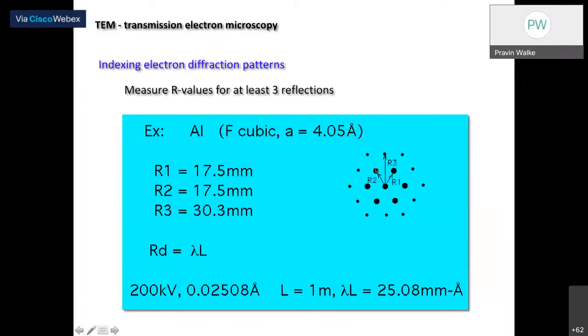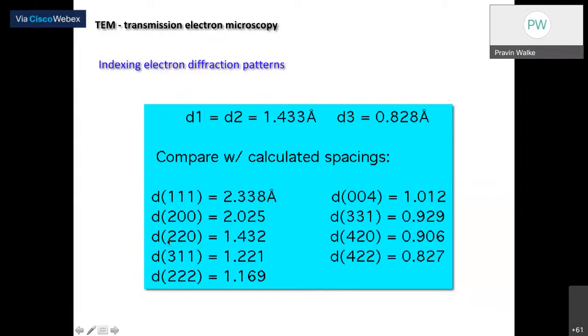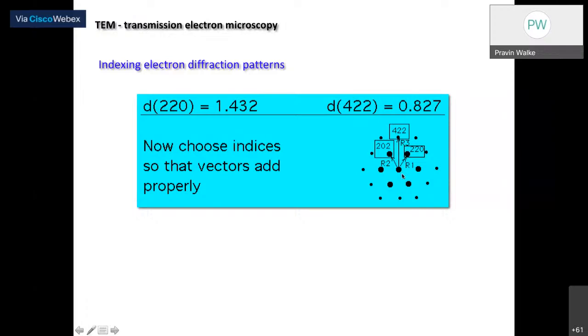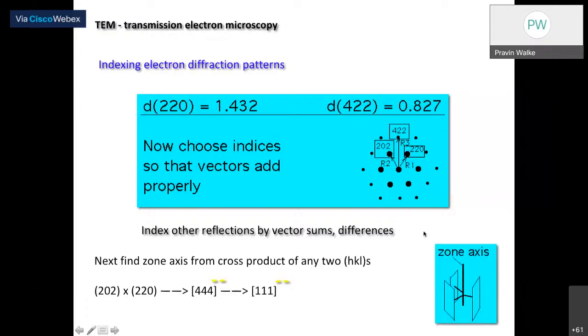Once you know this, let's say you have the diffraction pattern, you can simply find the distance between these consecutive neighboring spots, and you can find the R1, R2, and R3 values. Then by using the formula which we have already seen before, you can find the D values, right? D is the interplanar spacing, D1, D2, and D3 in the specific plane. Then you can compare these values with, for example, the D220 and D422 values, which are 1.4 and 0.8. If the distances between these spots match those D values, then you can simply index those spots, right? So indexing of the spots is very important. Then index other reflections by using the vector sum or difference formula, right?